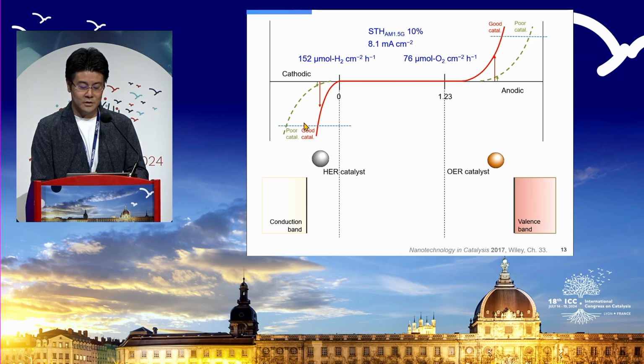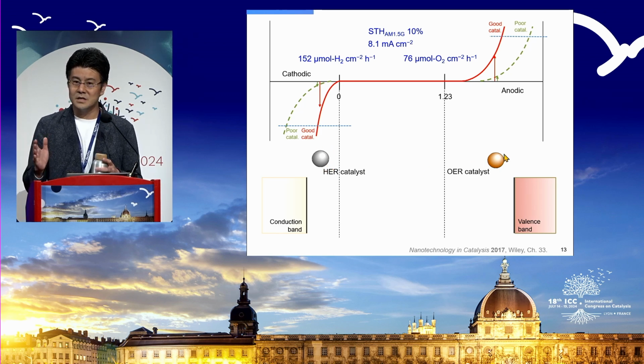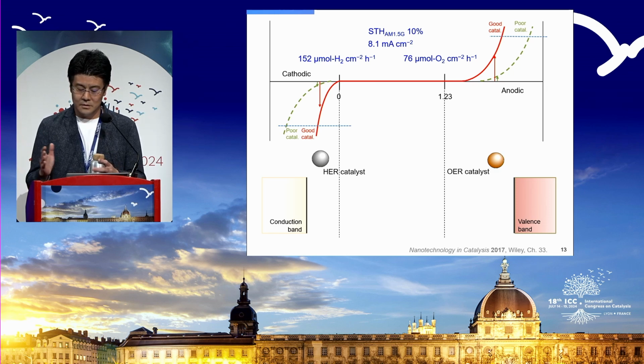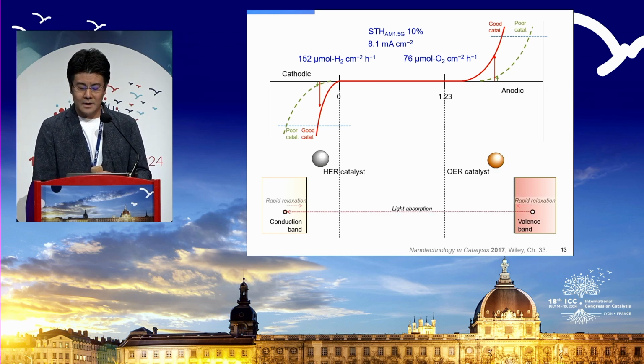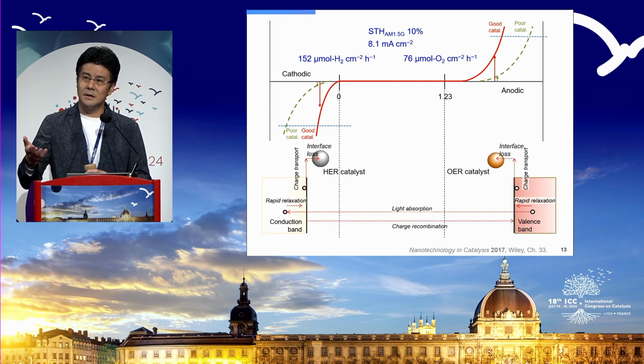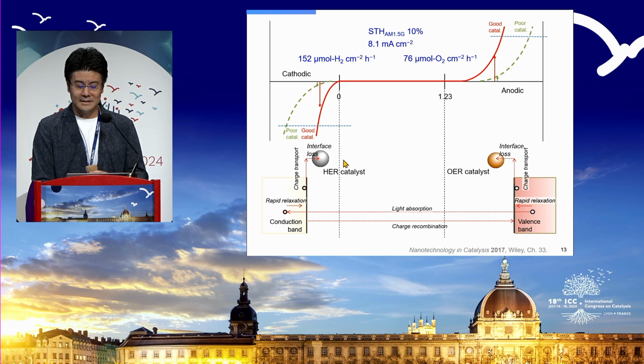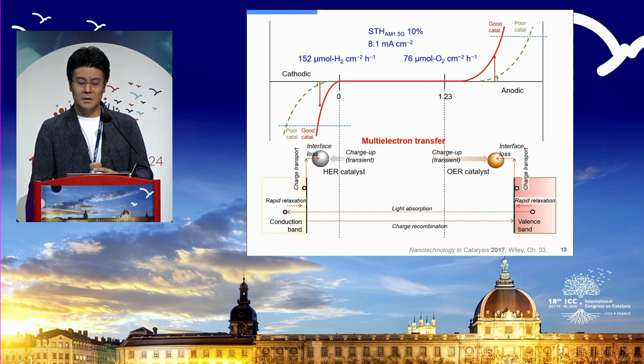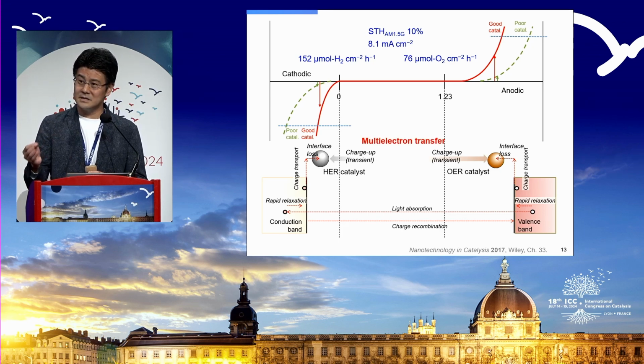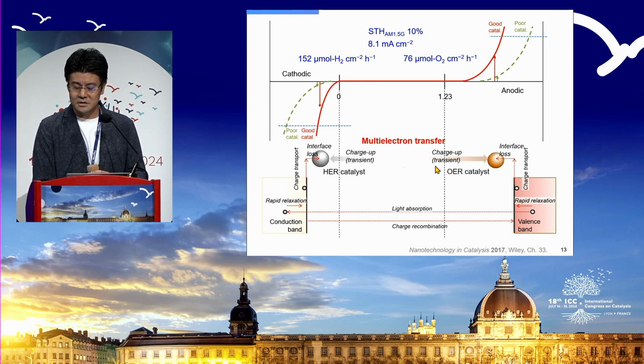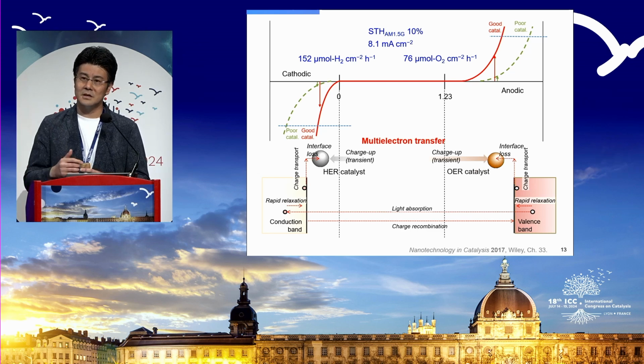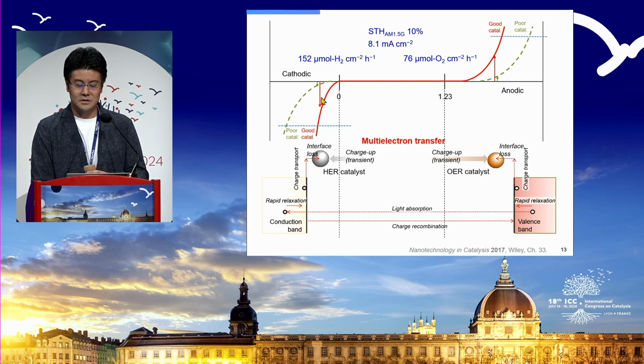But again, if you use a poor one, you will never achieve this 8 milliamp per square centimeter. So the first thing you need to do is select the best electrocatalyst, especially when you want to use visible light materials, with a narrower band gap. Then we have this light absorption. Then you keep charging up this electrocatalyst to maintain steady-state hydrogen evolution and oxygen evolution. That is because we have multiple electron transfer. The same catalyst site has to keep doing the job for multiple electron transfers. So this hydrogen evolution catalyst or oxygen evolution catalyst needs to sustain the potential, and that is at the potential that you want to achieve.